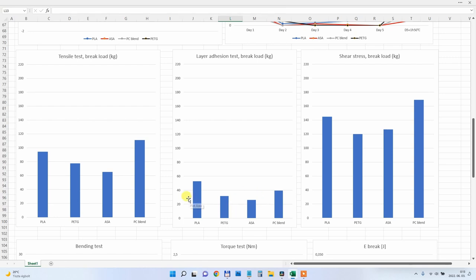So usually I consider that everything above 30 kilograms in this test is acceptable, but ASA had quite weak layer adhesion. PC blend, I was surprised a little bit. I thought it would be a little bit better, but this is also acceptable. In shear stress, the PC blend was the strongest, PLA and then PETG and ASA very similar.